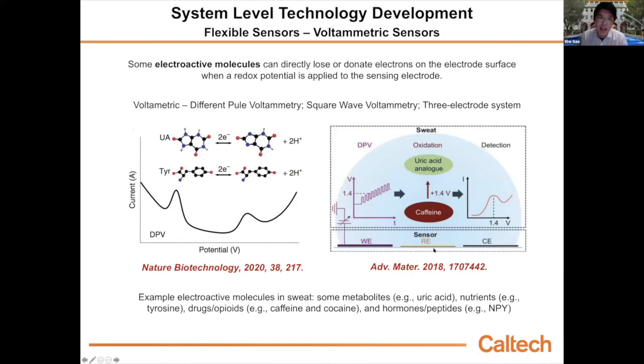To detect these electroactive molecules, we can apply certain voltammetric scans, such as differential pulse voltammetry. We can apply this voltage scan to oxidize the molecules at a given voltage. For example, if you scan DPV in a sweat sample, we can see two significant peaks. The first peak belongs to uric acid. Uric acid can oxidize at around 0.4 volt if you use a graphene electrode. And tyrosine, another key amino acid, can be oxidized at around 0.7 volt. By reading the current height, which is linear to the concentration, we can calculate the level of this biomarker in our body fluid. We can also use this to detect the drug caffeine in this case.